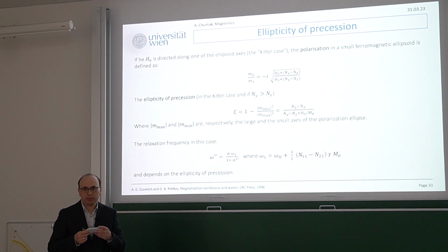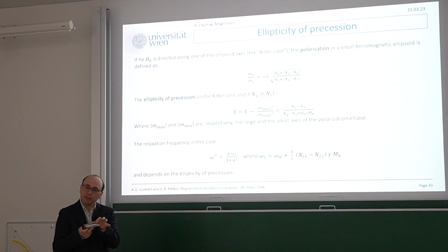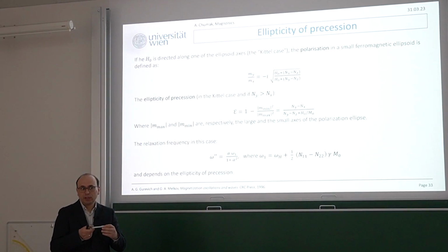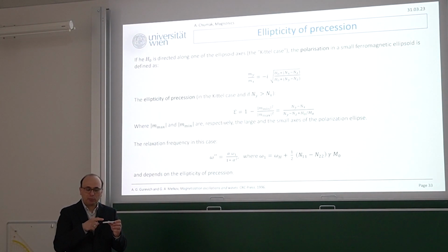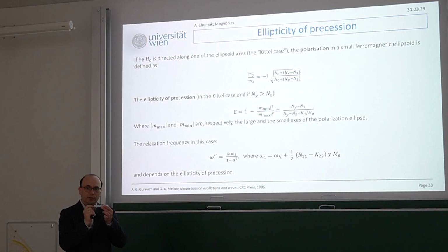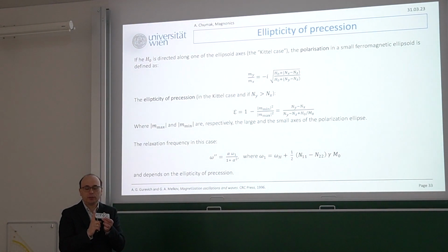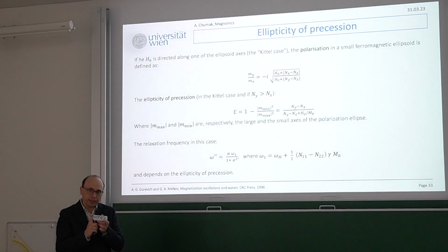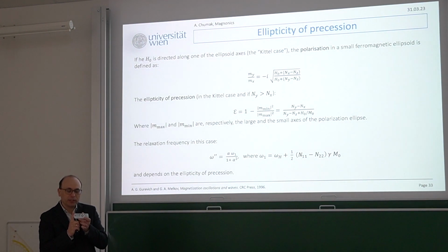And that's what usually happens. Our sample is, let's say, 1 by 1 centimeter, and the thickness is 10 nanometers. If you do it out of plane, you still say this is 0, this is 0, and this one collects all the magnetization. So it's a big shift in the FMR frequency by magnetization. That's more or less the limiting case, when all the magnetization is the largest.